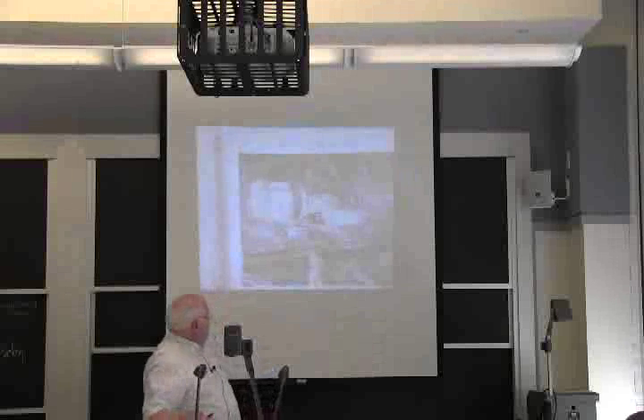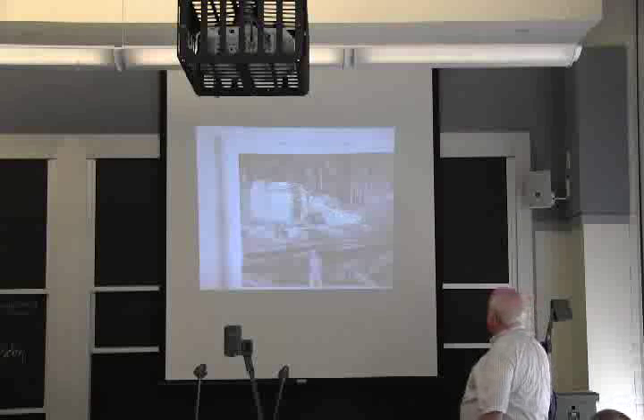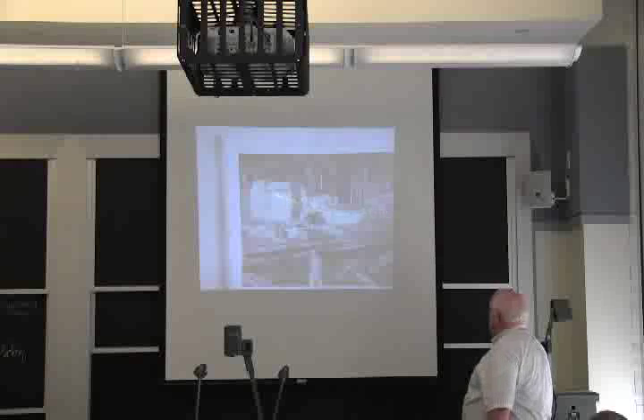And they had actually had to throw out the first 2 or 3 that they tried to make because they found defects in them after they forged them. And that's sort of what happened here. They were losing their shirts on this job. If you look, this is not forging of this particular ingot, but this just comes out of a steelmaking book. And it shows what happens when you're trying to forge a big piece of steel. This is an ingot, this is another ingot that probably has been partially forged, and they forge this much and then they put it back in the furnace.